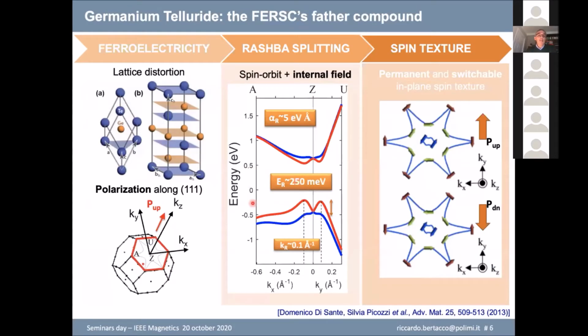Germanium telluride has this structure here, and due to some lattice distortion, you develop a polarization along the 1-1-1 direction, this pseudo-cubic description. Looking now at the energy dispersion of bands, you don't find exactly what you find in a free-electron model for, I'll say, 2-dimensional electron gas, but you see that the shape here is very similar to that of Rashba bands, ideal Rashba bands.